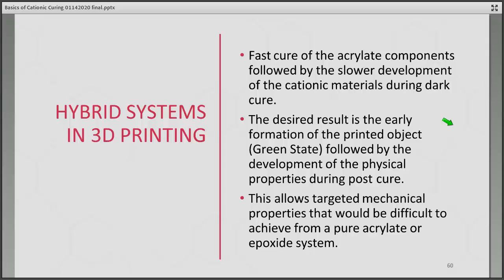Now, if you noticed early on when I introduced hybrid systems, I had some photos up on that slide, and one showed a selection of 3D printers on a lab bench. Another one was a 3D printed object. There's a reason for that: hybrid systems are becoming very popular ways of approaching formulations for UV curable 3D systems or additive manufacturing. It's because the fast cure of the acrylate components followed by the slower development of cationic materials during dark cure is a very useful combination to have when 3D printing.